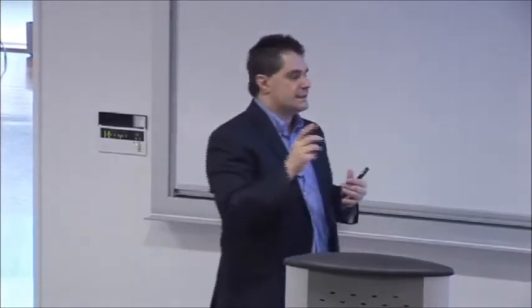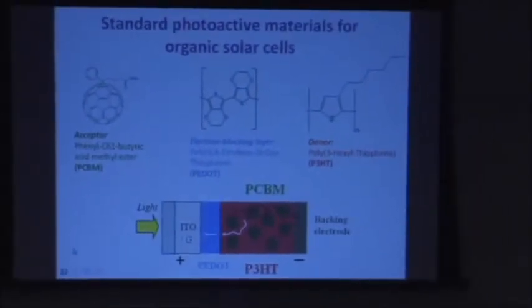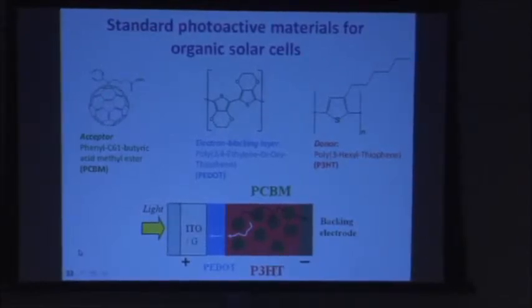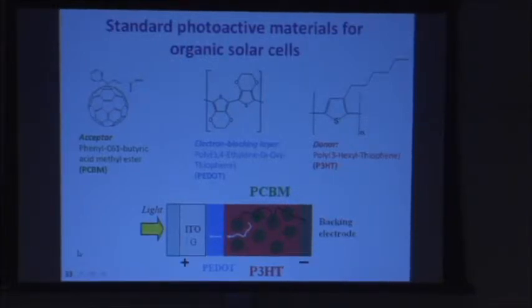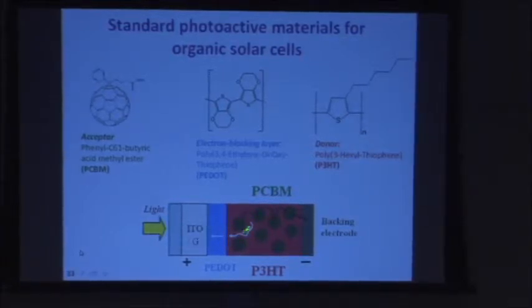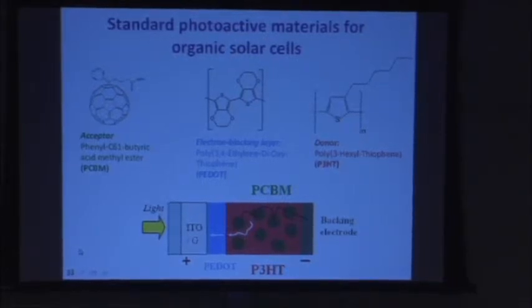So you need to prevent radiative recombination, where I create an electron hole pair in this material, and eventually this exciton recombines and emits the energy again as luminescence. I don't want that. So these excitons, these electron hole pairs, need to find an interface as soon as possible. So instead of using the typical p-n junction architecture, I use what is called the bulk heterojunction architecture. That means I mix P3HT and PCBM at the nanoscale, in a way that the typical length scale between the various components is of the order of the exciton diffusion length, a few nanometers, while in silicon it can be several microns.